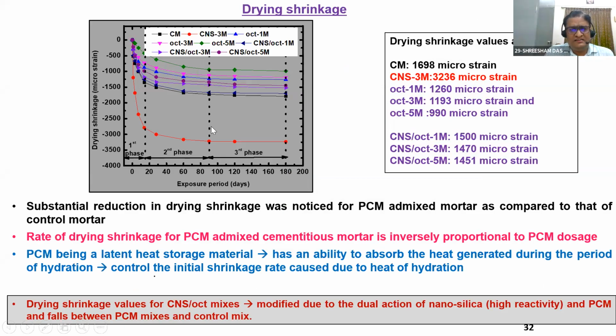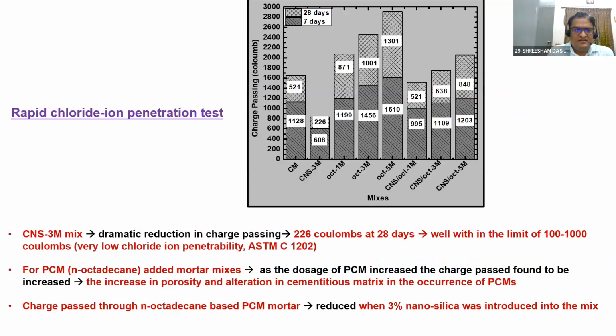Now you can see the red one, that is CNS, giving me the maximum strain, because it has 3% of nanosilica. As I was telling you, the moment you add nanoparticles, it gives the maximum shrinkage. Similarly, the green one, which is 5% of n-octadecane, is giving me the lowest shrinkage, because I am adding phase change material, and that is going to absorb the heat available within the cement system. Similarly, RCPT, anyway, this slide is not much important at this point.